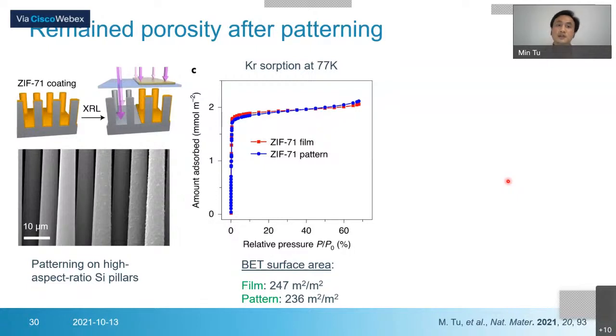And another question comes to us. We know MOFs are porous materials. So after patterning, can it still maintain this high porosity? So we did some porosity analysis before and after the patterning. If you remember, we can do the MOF coating on these high aspect ratio pillars, so we can have a very large area on a flat surface. If we have 1 square centimeter, we have more sample on the surface, then we can do the volumetric krypton adsorption. If you look at the red one, it is a MOF film coated on these pillars, and it shows this type 1 adsorption isotherm.